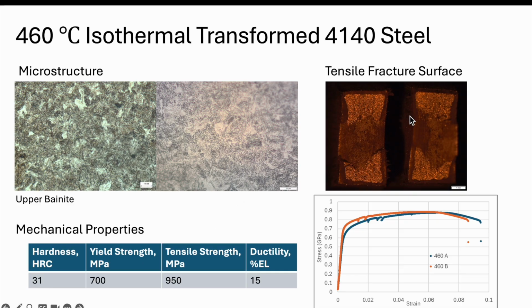And again, if we look at the fractured surfaces, we see a change in shape, so it's no longer perfectly rectangular. We see kind of the cup and cone structure here. Again, the flat surface in the middle tends to denote a more brittle sample, and some of these areas you can see in here represent the more ductile nature of it. So a mix of brittle and ductile, a higher percentage than the previous samples.